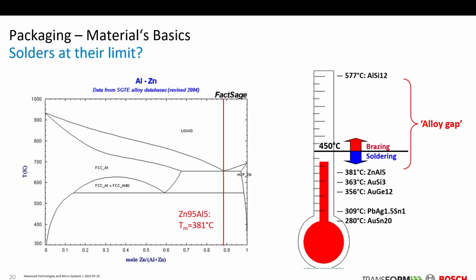So soldering: it's quite hard to substitute the lead-containing one. What about brazing? Brazing needs a large temperature. The lowest melting brazing alloy is this one at 577 degrees C, aluminium-silicon 12. So we have something like an alloy gap. This is the official border regarding the homologous temperature. Lower temperatures are related to soldering materials, higher temperatures to brazing. But here is something like an alloy gap. Here we have no material solution, it's not existing. The periodic system is limited here.